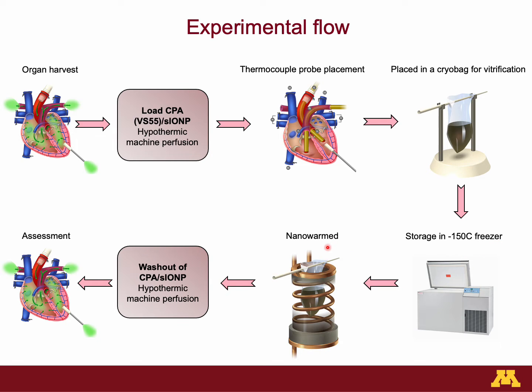Then we perform the nanowarming, which uses a radiofrequency coil to rewarm the organ quickly and uniformly to avoid ice crystallization and convective failures. After that, we unload the CPA and silica-coated iron oxide nanoparticles from the heart using hypothermic machine perfusion. And finally, we perform an assessment on the heart.